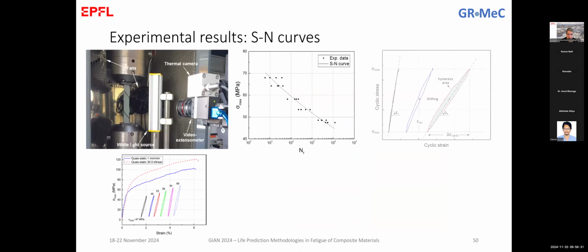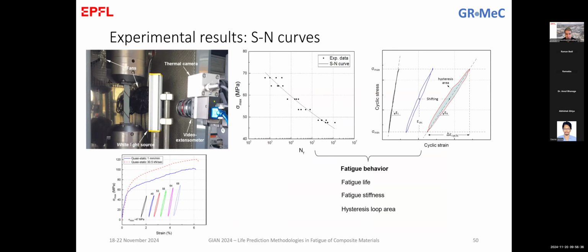So fatigue testing, we'll just open this one. Fatigue testing was, as usual, in the chamber to keep the temperature low. We were also measuring, if you see here, we have a thermal camera monitoring the temperature of the specimen. We had this video extensometer camera to take photos of the specimen and be able to extract the strains at the end. And we also have a light source to improve